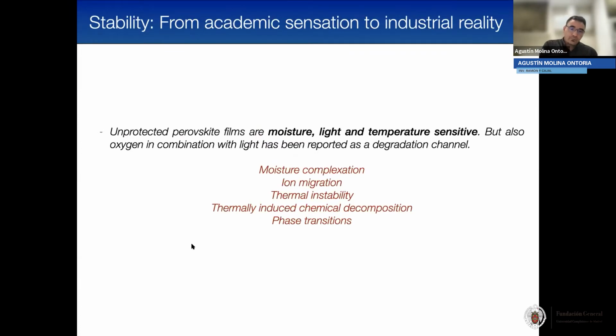Well, perovskites are sensitive to heat, to moisture, and, ironically, to light. So there are many channels of degradation, such as moisture, complexation, ion migration, thermal instability, thermally induced chemical decomposition, and phase transition. So this is a solar cell that is sensitive to light, which is catastrophic. We need to obtain a stable perovskite if we want to go from academic sensation to industrial reality. We have to tackle the stability of the perovskites.